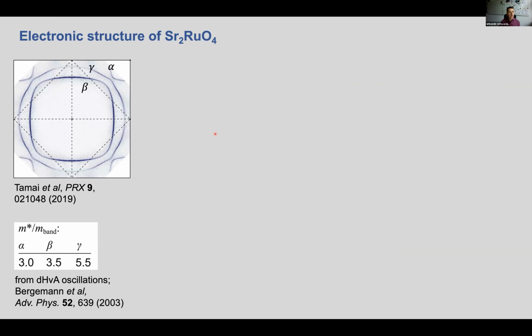So to show concretely what happens, these are the Fermi surfaces of strontium ruthenate. This is from very high resolution photoemission data from the Baumberger group at the University of Geneva. We have two electron-like Fermi surfaces, the beta Fermi surface and the gamma Fermi surface, and then one hole-like Fermi surface, this alpha pocket in the corners. Quantum oscillation data show that there's a modest mass enhancement. The masses on the alpha and the beta sheets are enhanced by about a factor of 3 from bare band calculations, and of the gamma sheet by a factor of 5.5.